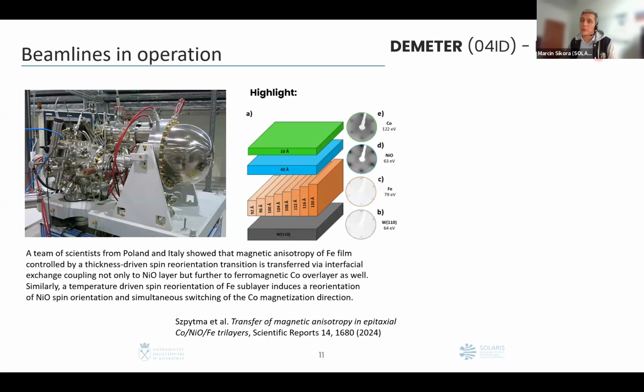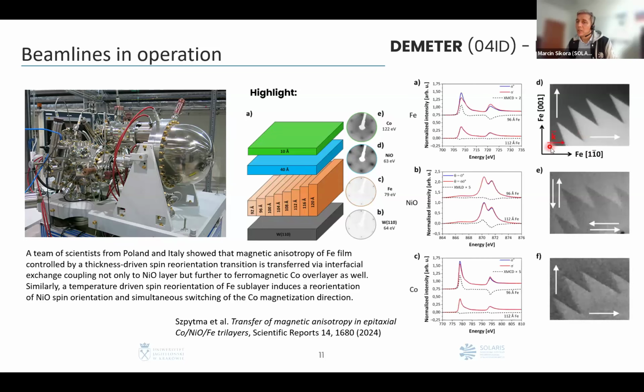The very first microscope is the photoelectron emission microscope. So with the full field, we excite our system, and then we probe the photoemission spectrum, but with selectivity to different sides of our sample. So in a field of view of about 50 micrometer radius, we can see with the resolution of about 40 nanometers the chemical composition and also magnetic composition in this case of our film.